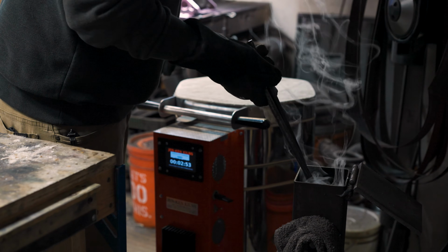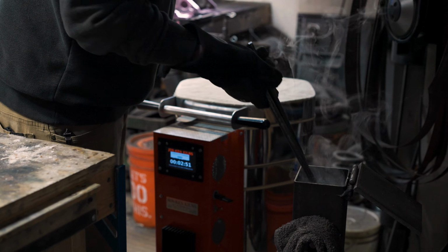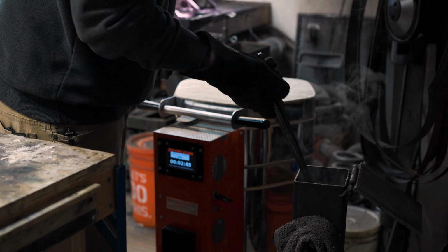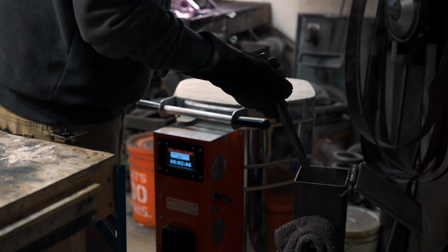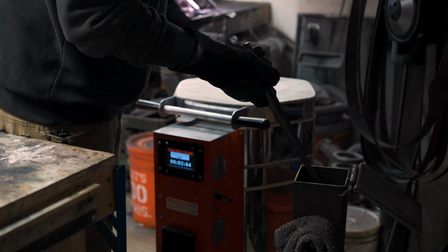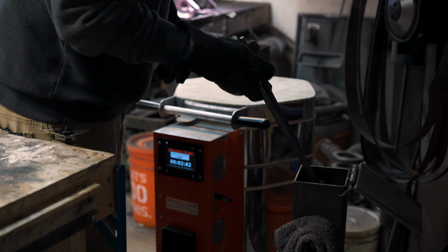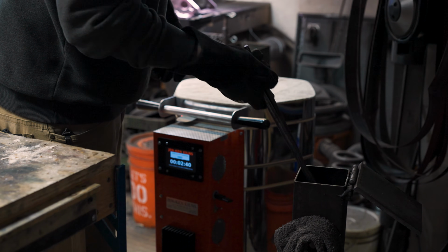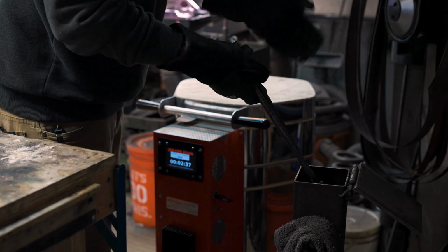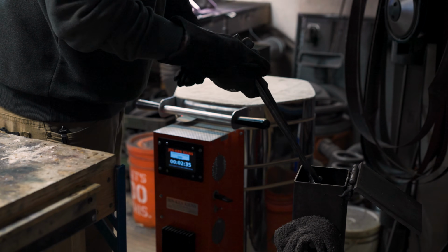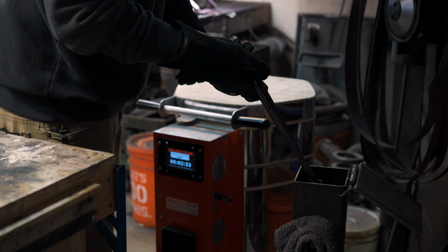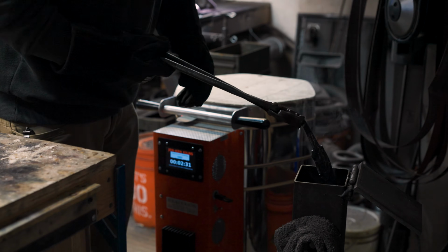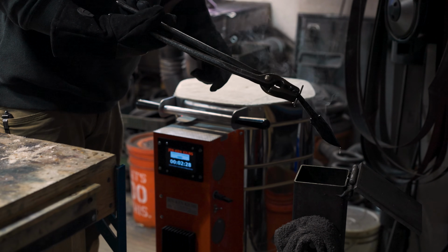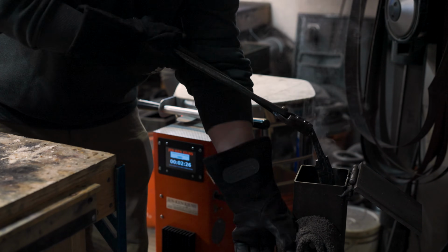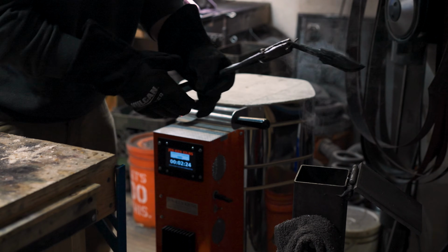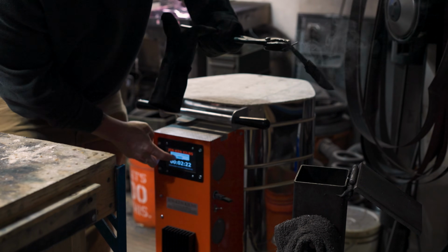So quick quench and agitate it just a little bit for about 10 seconds. You don't want to build a vapor barrier around it and keep it from cooling as quickly as it could. And when you agitate, I just go straight up and down, not side to side. They say it can warp the blade by going side to side. I don't know if that's really true or not, but I'll pretend it is. So once, let me turn this off really quick.